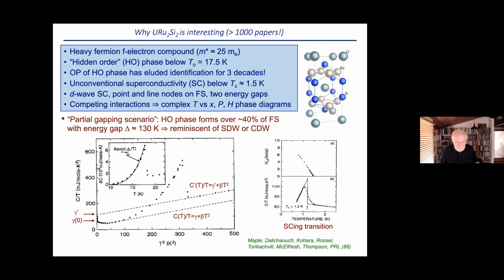So uranium ruthenium 2 silicon 2 (URu2Si2) is a heavy fermion f-electron compound. Effective mass is about 25 times the free electron mass. Hidden order phase occurs below 17.5 Kelvin. As I said, the order parameter has eluded identification for now more than 3 decades. It exhibits unconventional superconductivity, which appears to be d-wave superconductivity. It has both point and line nodes on the Fermi surface and 2 energy gaps. I'll show you this in a moment. And then the competing interactions, of course, give rise to these complex phase diagrams.